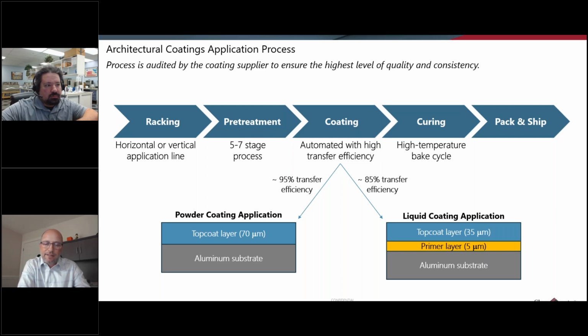A vertical line is optimized for running aluminum extrusion. It's what it sounds like. You have a machine where you set these aluminum extrusions, which can be up to about 30 feet long, and it will actually turn them vertical and make almost a wall of aluminum extrusions, and they go through the line that way. Those are quite a bit more expensive, but the advantage is they're a lot more efficient. Your coating efficiency is better because you're coating almost a wall of material as opposed to stacked pieces. And your throughput is much faster because it's designed to move that through the process a lot faster, since all you're coating really is aluminum extrusions.